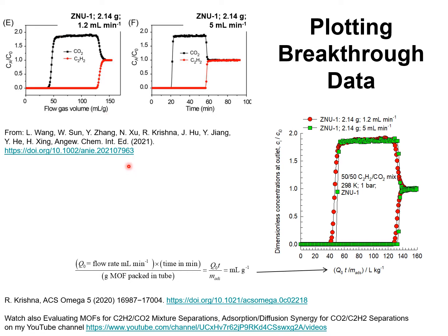I am going to make a plea to researchers presenting breakthrough data to use consistently a modified time parameter defined as the actual time in minutes times the flow rate of the gas mixture entering the bed in milliliters per minute, divided by the mass of adsorbent in the bed in grams of MOF. This parameter will have the units of milliliters per gram or liters per kilogram.